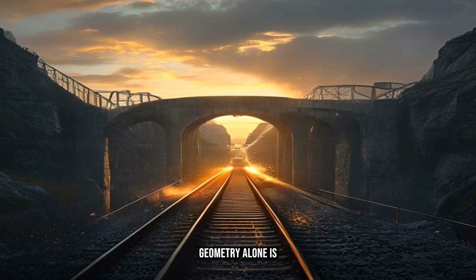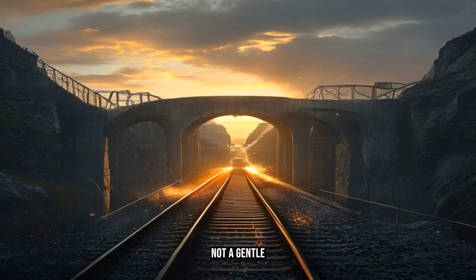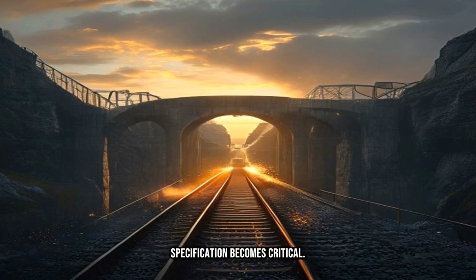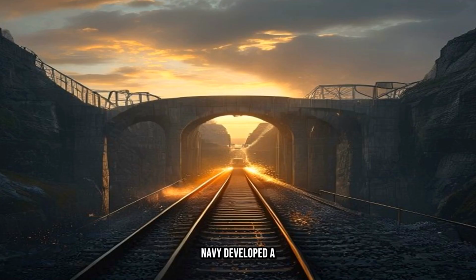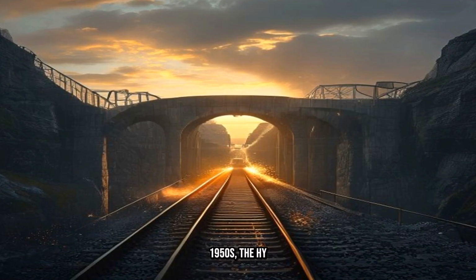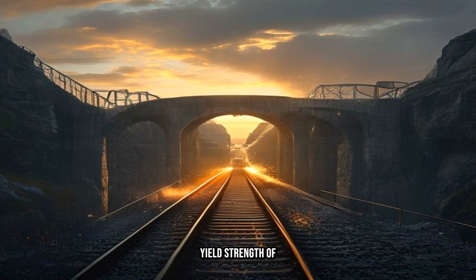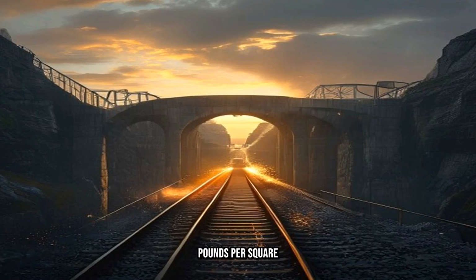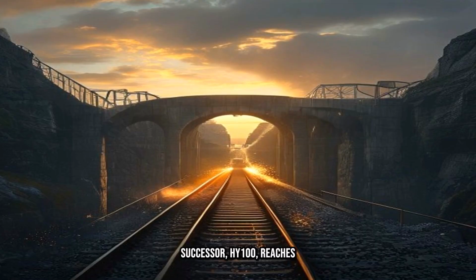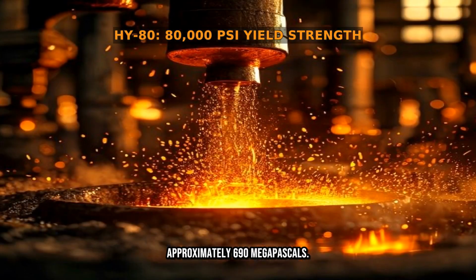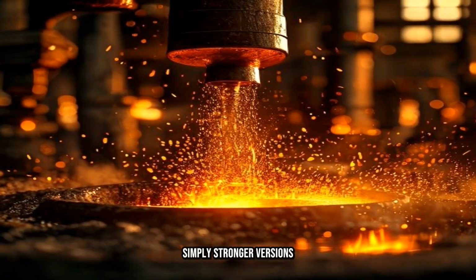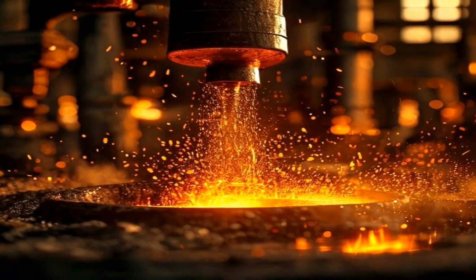But geometry alone is not enough, because the ocean is not a gentle loader. This is where the steel specification becomes critical. The United States Navy developed a steel grade called HY-80 in the 1950s. The HY stands for high yield, with a yield strength of roughly 80,000 pounds per square inch, or about 550 megapascals. Its successor, HY-100, reaches approximately 690 megapascals. These are not simply stronger versions of structural steel.